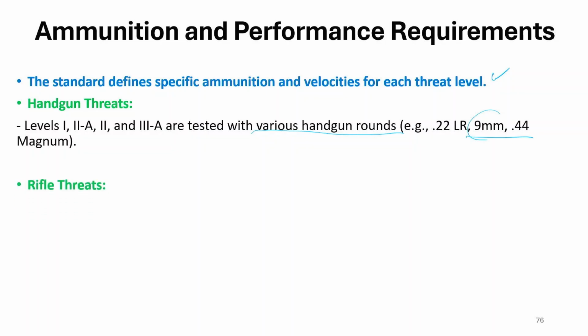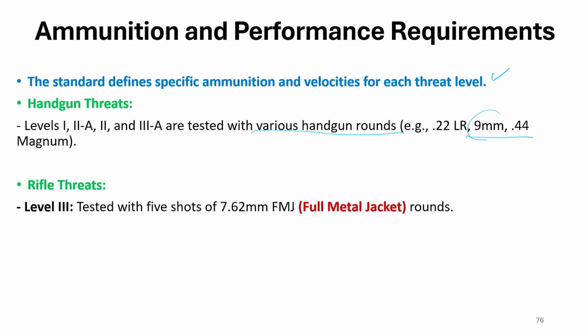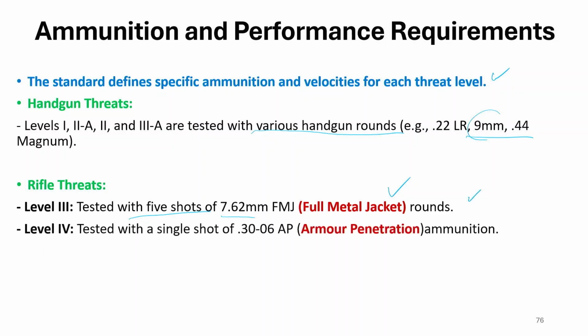3A, and the higher threats, which is rifle threats, level 3 is tested with 5 shots of 7.62 millimeter full metal jacket round. So, that is the specified type of threat, the rifle. This is required, and level 4, which is more severe, armor penetration rifle, is tested with a single shot of 0.30-06 AP armor penetration ammunition.